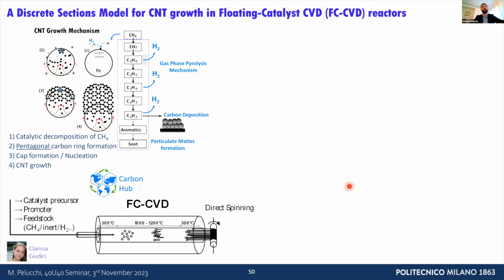So we typically have a catalyst precursor, ferrocene, that is sprayed into a flow reactor called a floating catalyst chemical vapor deposition reactor. It starts to nucleate and provides the active sites, catalytic sites, for the carbon to deposit and grow in the form of nanotubes.